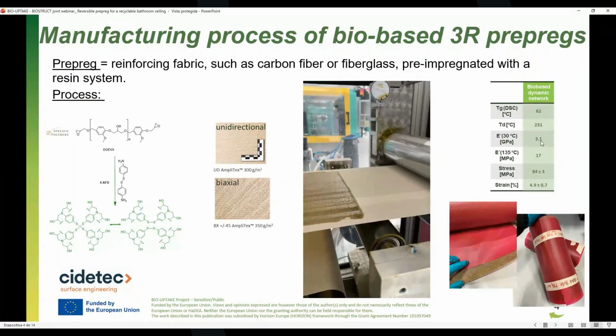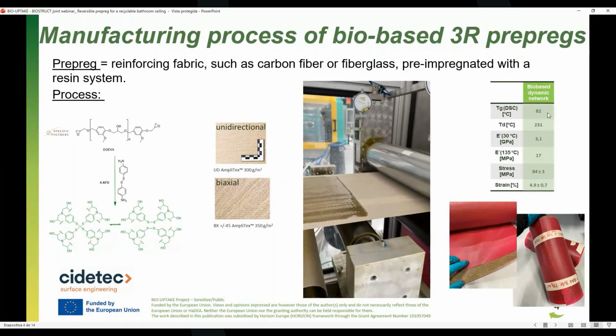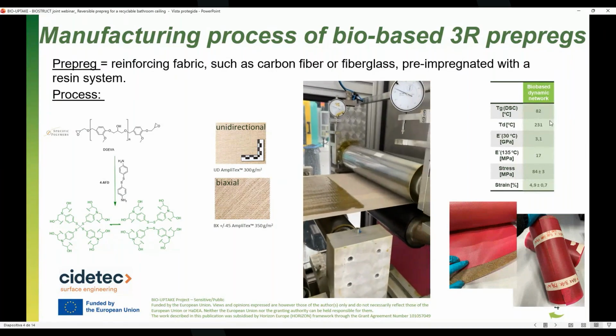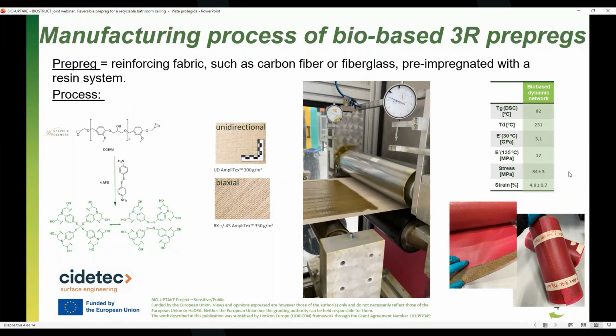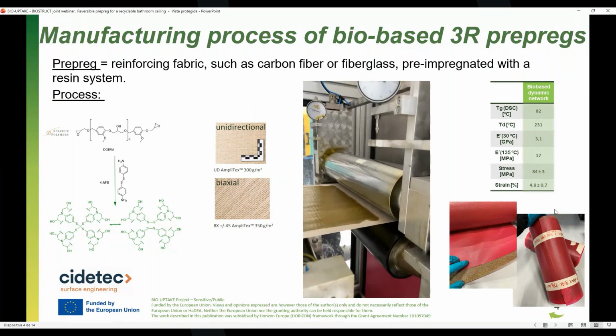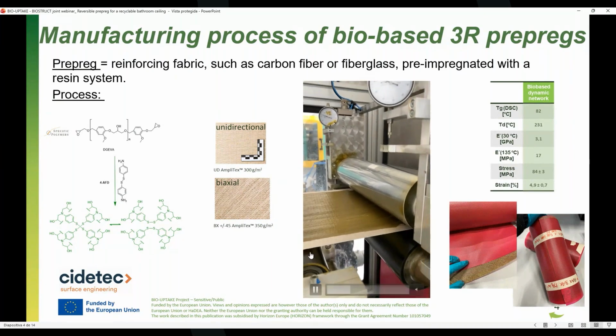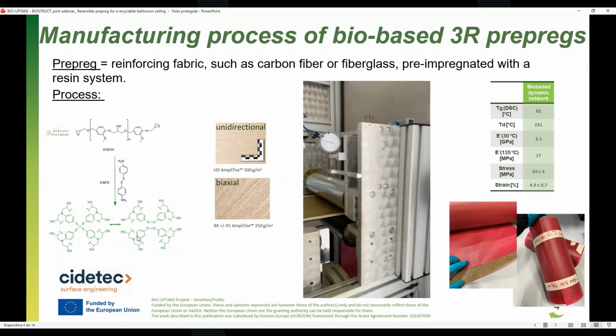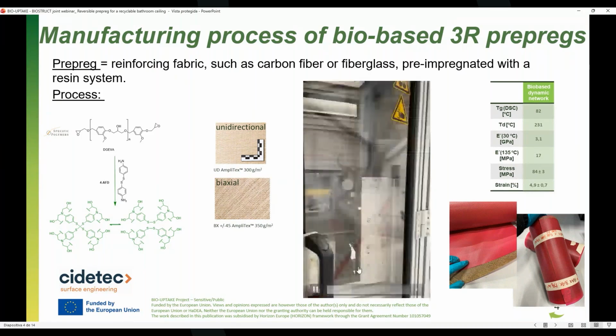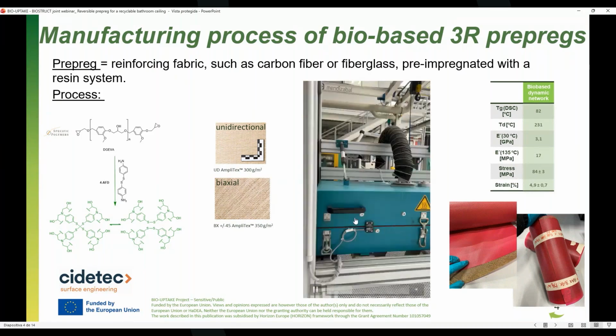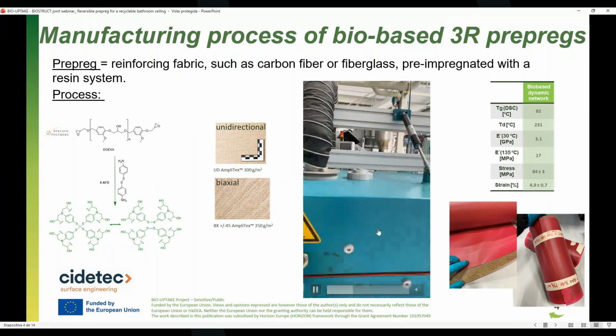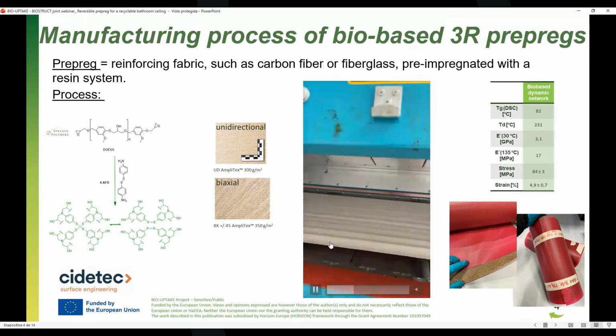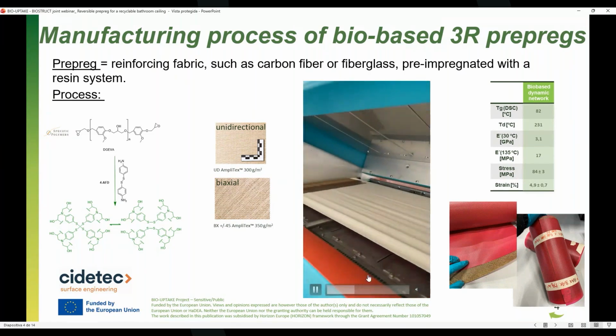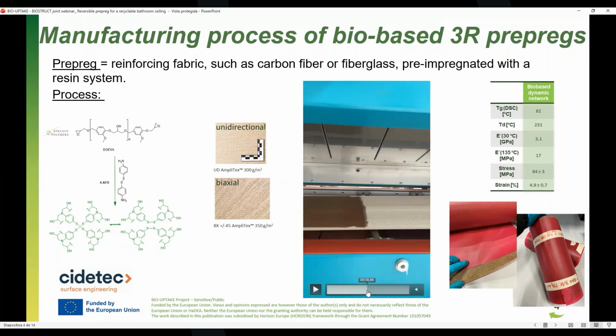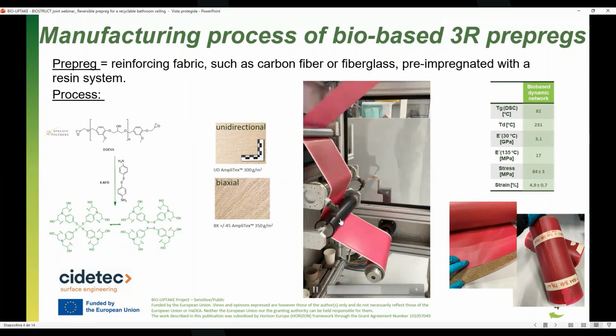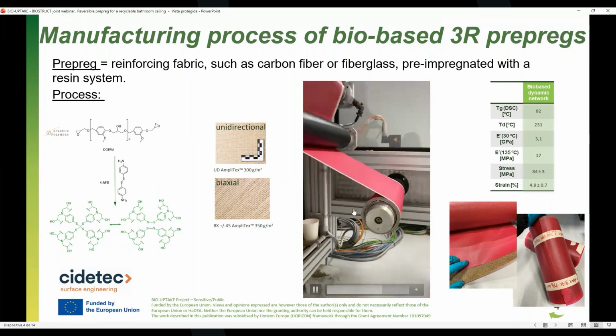In this table, we can see the properties of the dynamic network, which are very similar to what we could obtain if we used a common DGEBA resin instead of the Specific Polymers one. So here the impregnated fibers go through. Sorry for the quality of the video, it's not very good, but they go through the whole process, and then they come out, and we collect it here in a roll.